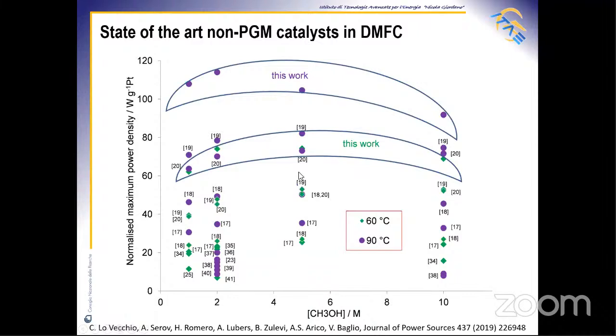The maximum power density values normalized against the platinum content in the MEA, only present at the anode side in the platinum ruthenium alloys used as catalyst, were compared with the current literature regarding this type of catalyst in direct methanol fuel cell applications. Different methanol concentrations, 1, 2, 5, and 10 molar, were analyzed in this comparison.